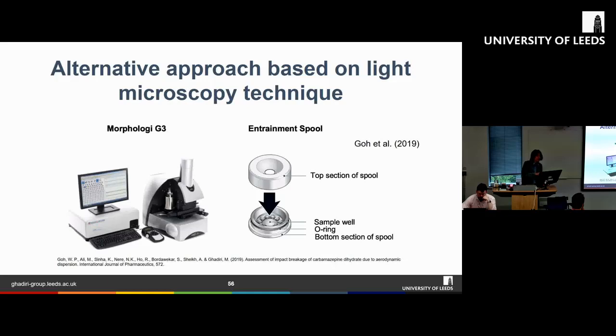A commercial device available for this type of analysis is the Malvern Morphologi G3, as you can see here. How it works is that we put some material in this well here. We apply a pulse of air from the top, and as a result, particles collide against the wall of this dispersion spool, and then they break.